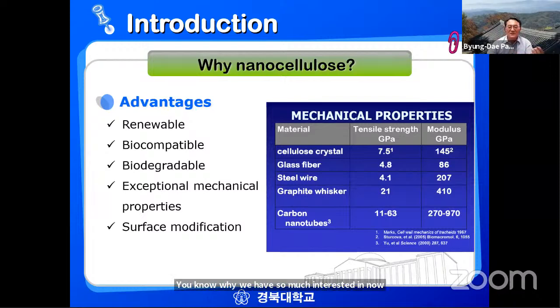Why are we so much interested in nanocellulose? The nanocellulose from wood is renewable, biocompatible, and biodegradable, and they also have exceptional mechanical properties. Also, we can change their surface to make it compatible with polymers and some other materials as well. For example, the nanocellulose crystal has very high tensile strength, 7.5 gigapascals, and 145 gigapascals as modulus. That's exceptional. It's better than glass fibers. That's why many people are interested in nanocellulose.